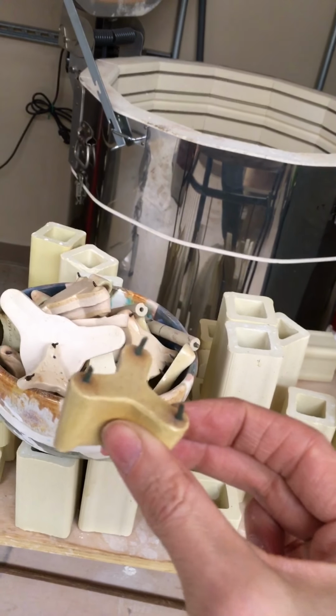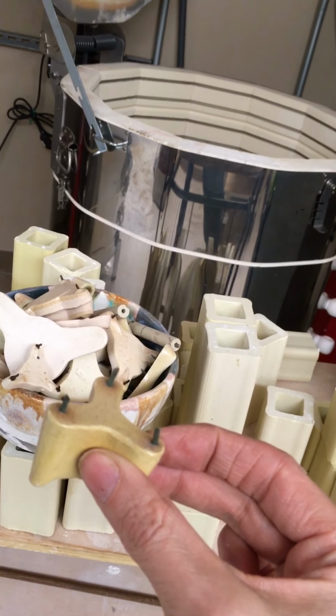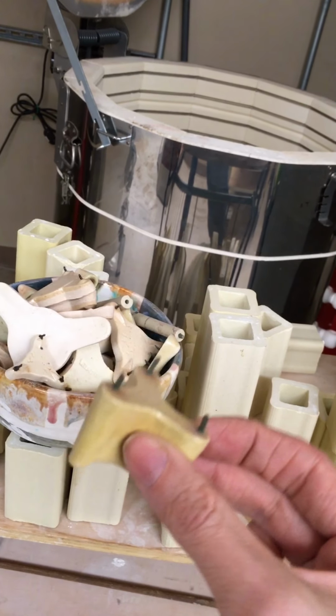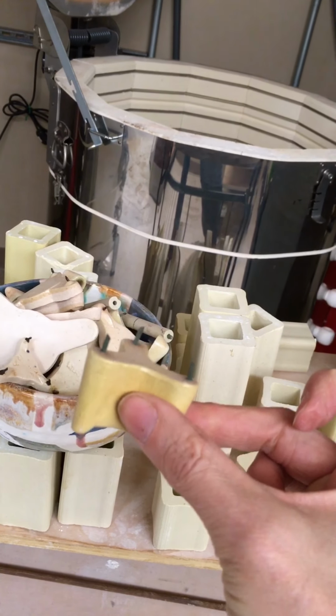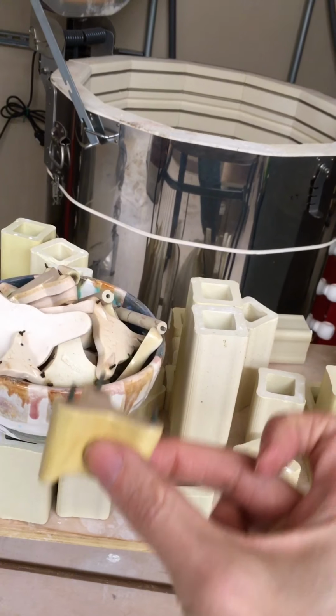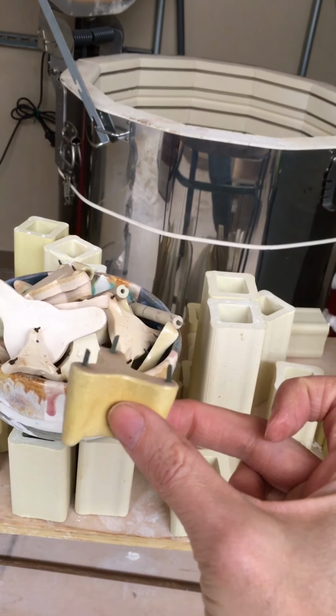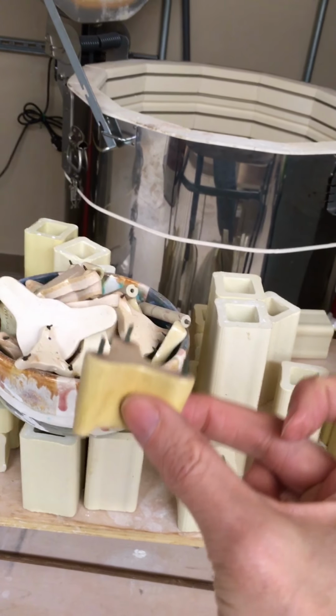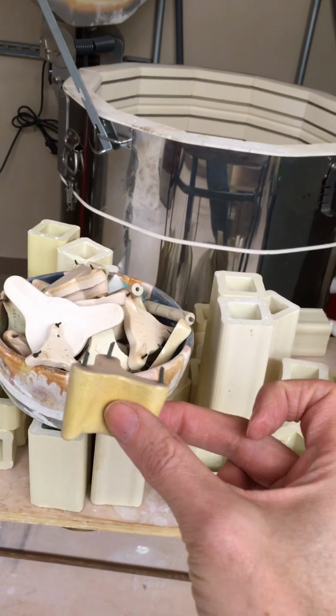We never use these in our cone 6 kiln because at cone 6, we're firing our clay body at what we call complete maturity. And so these little wires will actually sink into the clay and be very hard to release or pry off. Sometimes, but rarely, I use these to stilt some low fire work. Please do not use these stilts without my permission.